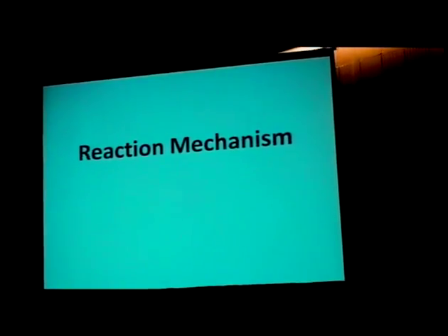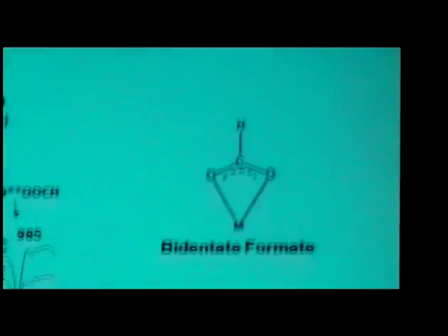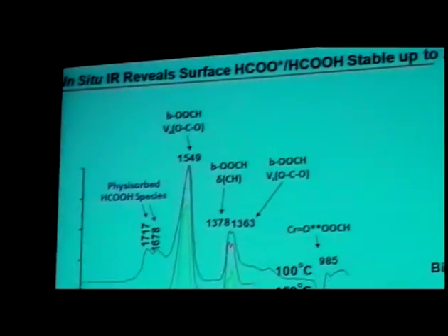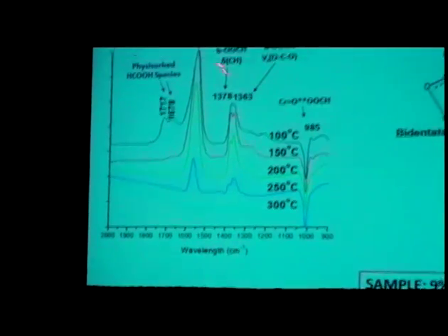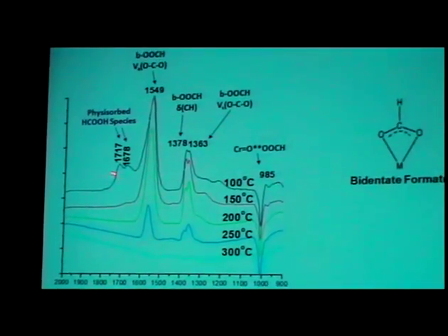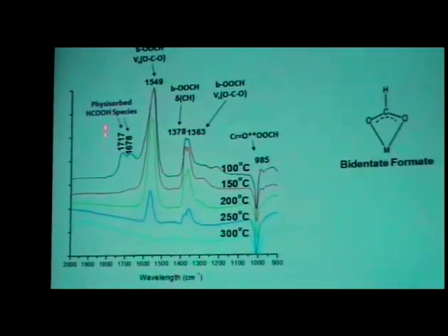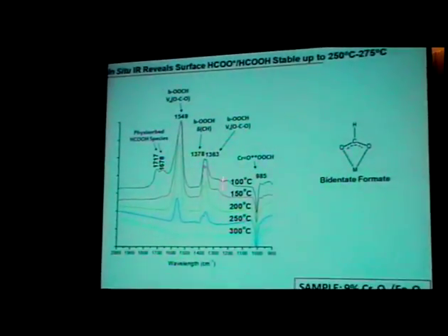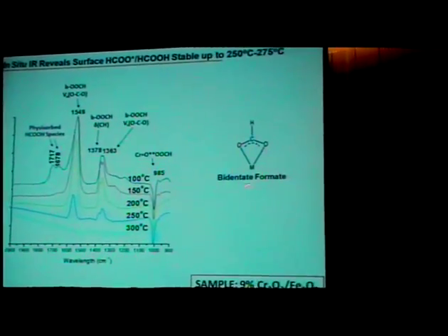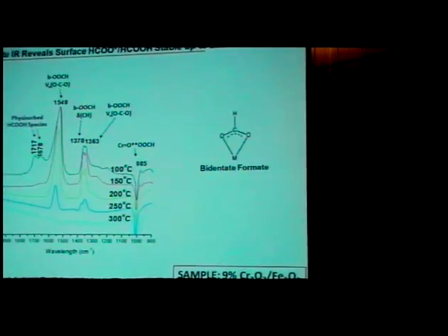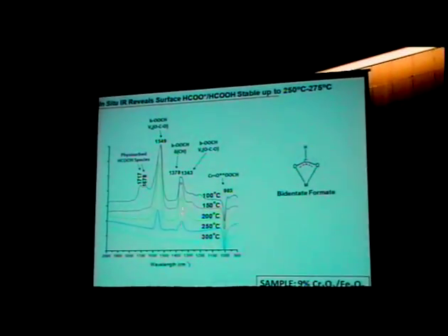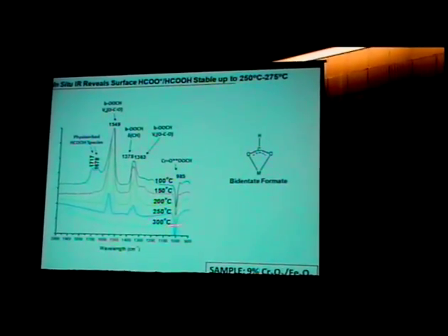Let's look at the reaction mechanisms. Remember, there were two reaction mechanisms. Can we get information about one versus the other? Since formate was the dominant species invoked for the associative mechanism, we adsorbed formic acid on iron chromium. And here are the vibrations, and some physisorbed, a residual amount of physisorbed formic acid. But as you heat it up, all you're left with is this bridged, this bidentate formate species on the chromium iron catalyst. And the important point here is that this species is stable till about 300 C,